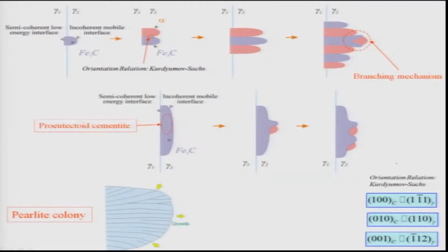Let us assume there are two grains of gamma, gamma 1 and gamma 2 here, and let us assume that Fe3C is the phase which starts nucleating on the grain boundaries. You can also assume that alpha nucleates at the grain boundaries. And as you know, Fe3C has a large carbon concentration, 6.67 weight % carbon. On the other hand, alpha has a very low carbon concentration. It is about 0.02% at 727 degrees Celsius, and at room temperature it is almost 0. That is what is seen in the phase diagram.